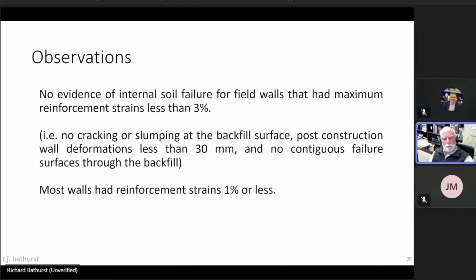Other evidence related to failure conditions was that in the database of instrumented field walls, we found that there was no evidence of an internal soil failure surface if the maximum reinforcement strains were less than 3%. So that was an important indicator of the partition between working stress conditions and limit equilibrium or failure conditions. That meant keep the strains to less than 3%, and there'll be no slumping, no continuous deformations in the wall. In fact, for most walls that we've monitored in the field, the reinforcement strains under operational conditions, the conditions that the wall was designed to resist for its lifetime, are almost always less than 1%.